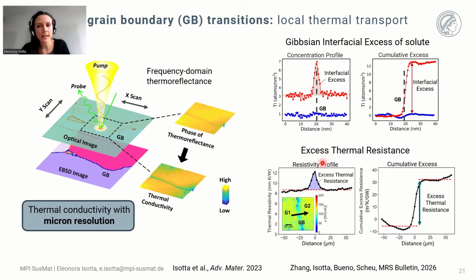That is an estimate for the thermal resistance of the grain boundary. To do so, we take the thermal resistivity and integrate the local thermal resistivity minus the constant value of thermal resistivity in the grain. By doing so, we obtain this excess thermal resistance that we can attribute to specific boundaries, and that is our proxy for the thermal resistance.